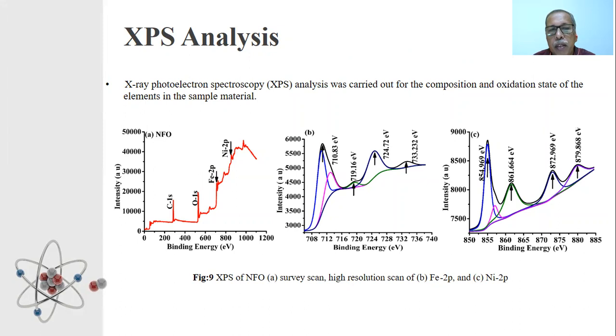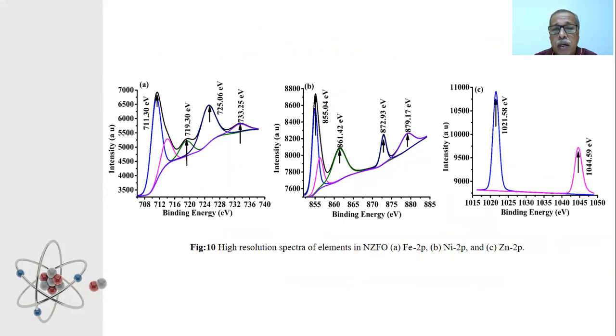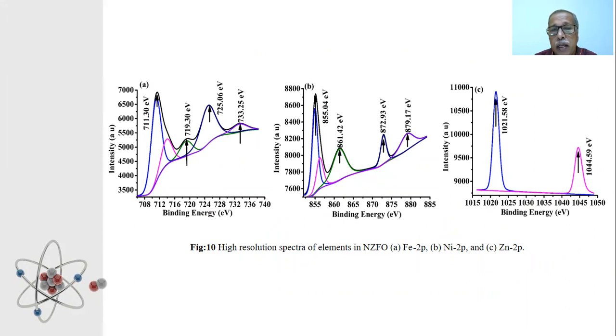Fe2p is found to show doublet structure. Each component peak of the 2p pattern shows deviation from perfect Gaussian nature which means more components are present in each peak. They are separated using software technique. These component peaks are identified using colored patterns in the following figures. The position of the peak, the peak area, and the full width at half maximum are tabulated and compared with the standard reference to identify the oxidation state of the cation as Fe3+, Fe2+, Ni3+, and Ni2+.